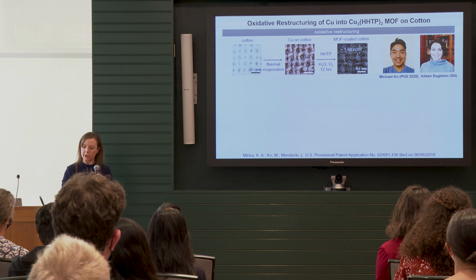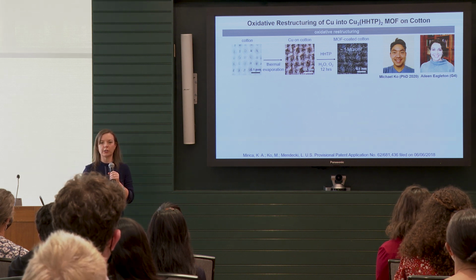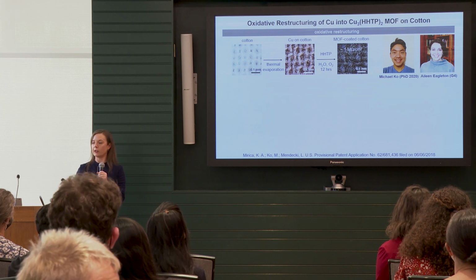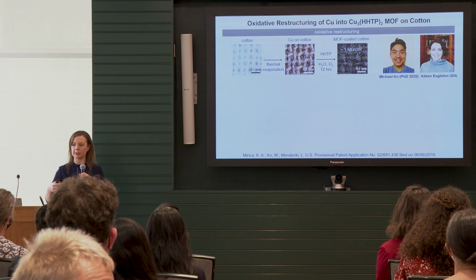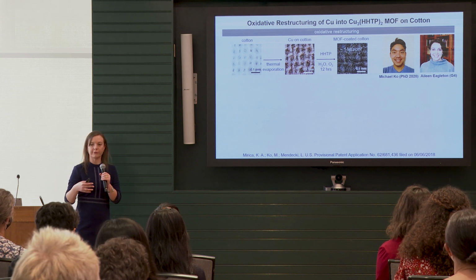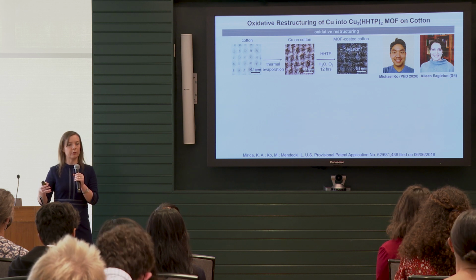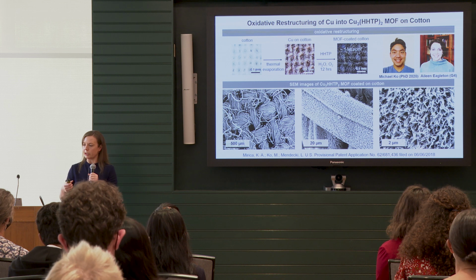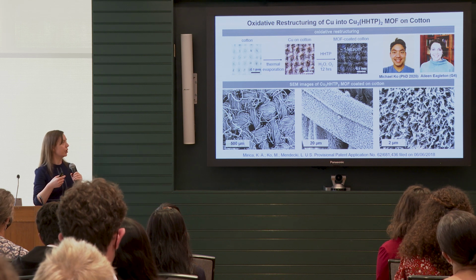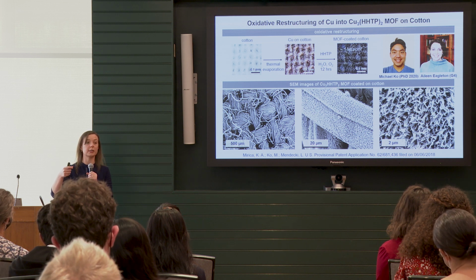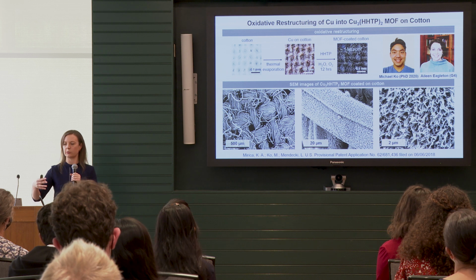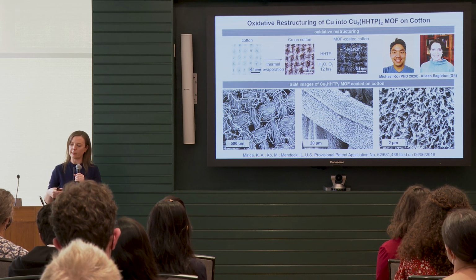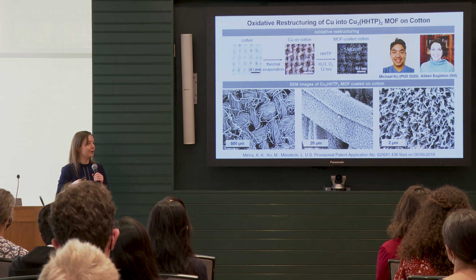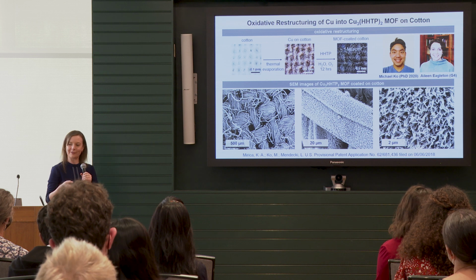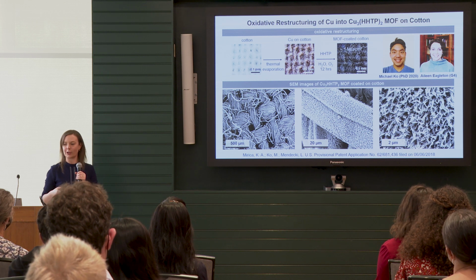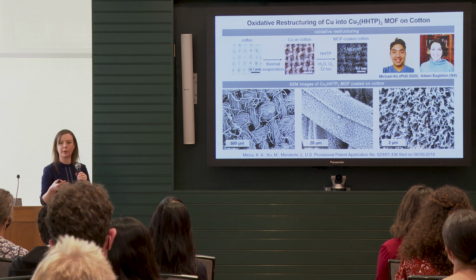While working on the project of textile integration, we've also serendipitously discovered another method for immobilizing framework materials on textiles. And this method involves solid conversion of pre-deposited copper metal into the framework material. What turned out to be really interesting about this methodology is the beautiful orientation of the framework crystallites with respect to the cellulose fibers, which is templated by this reaction and the pre-deposition of copper. This was not by design. This was an accidental discovery in the laboratory by one of my first graduate students, Michael Ku, who simply observed this reaction as he was trying to work with copper-based electrodes.